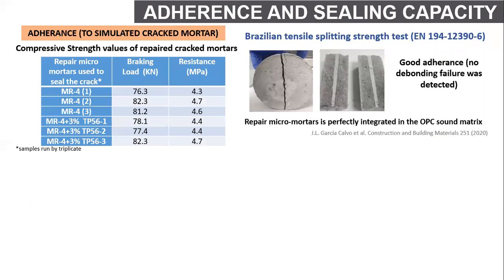Well, so as we have commented before, we have tested the adherence of these repair micromortars to the traditional OPC substrates. So for that, the bigger specimens, cylinders with a crack of 9.5 millimeters, were sealed with two formulations, the mortar reference and the same mortar with the TP56 product with the highest proportion of polydimethylsiloxane. And once these cracks were sealed and the mortars were cured for 28 days, these mortars were subjected to the Brazilian tensile splitting strength test.